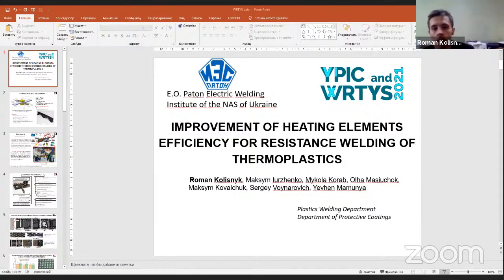So, as you can see from the pictures, the surface of the unmodified heating element is smooth. In this case, the specific area of contact between polymer and the heating element is low. Otherwise, modified heating elements, as you can see from this picture, have high specific area.